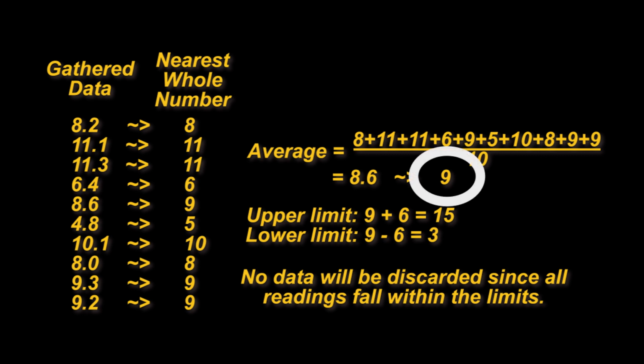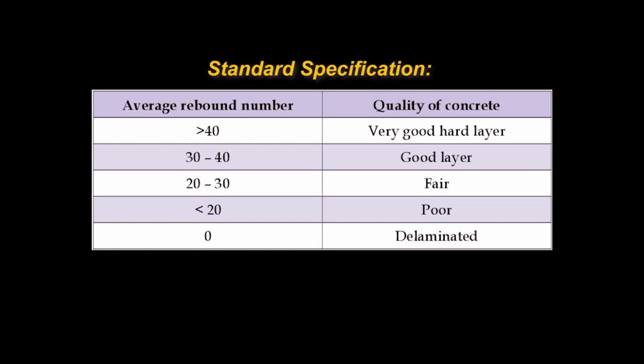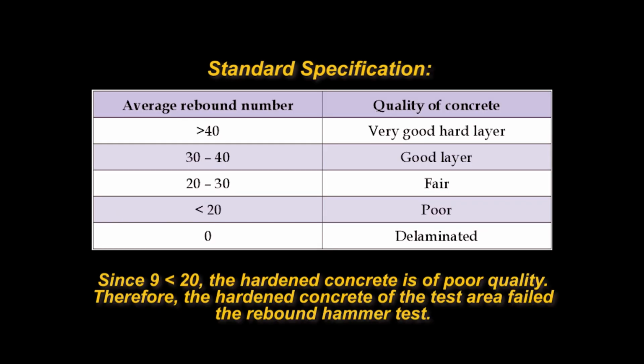The standard specification is as follows. Since the rebound number 9 is less than 20, this indicates that the hardened concrete of the test area is of poor quality. Therefore, the hardened concrete of the test area failed the rebound hammer test given its specification.